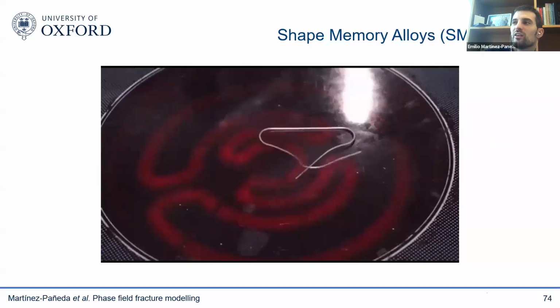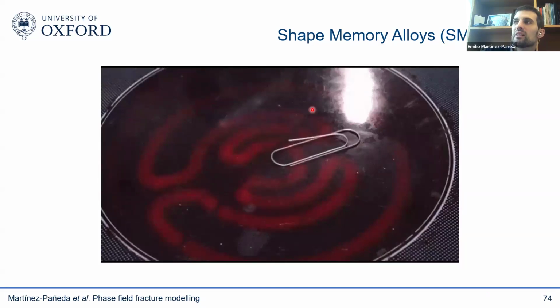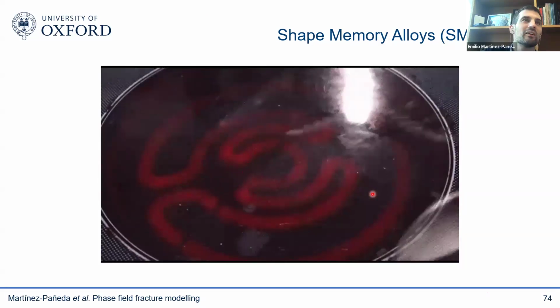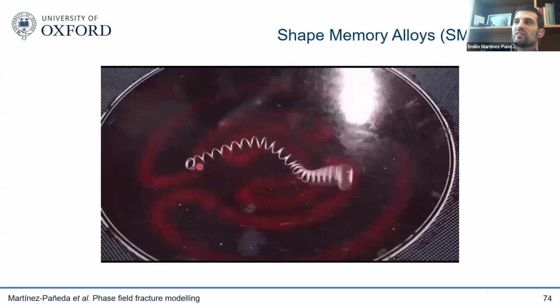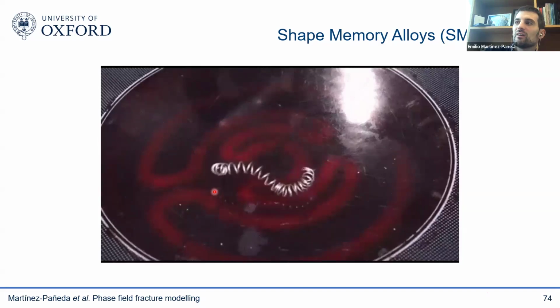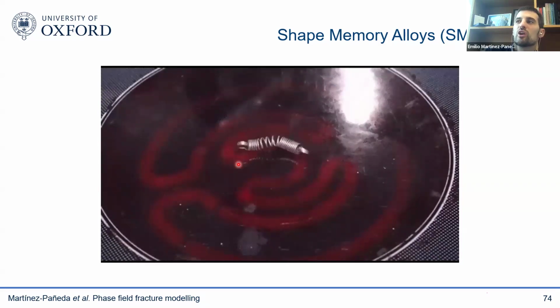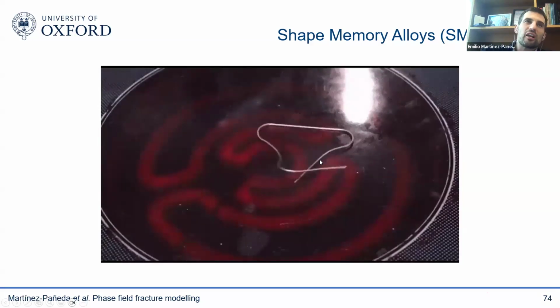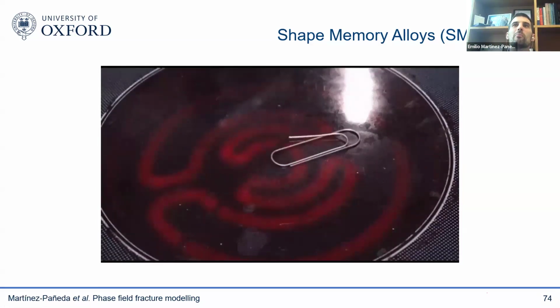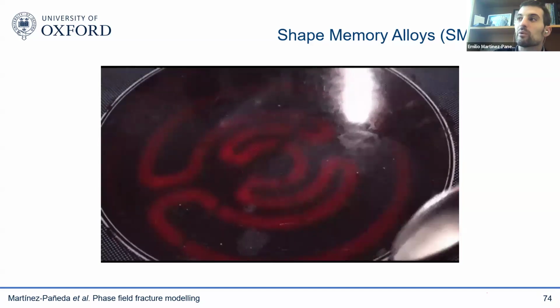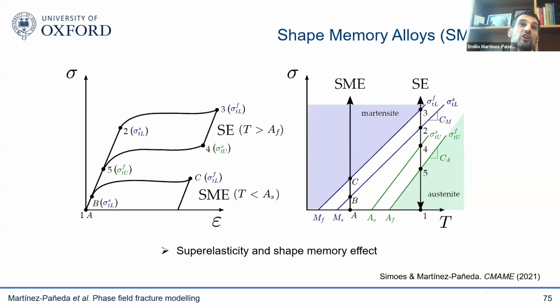So as you can see in these funny videos here, you can take a clip, deform your clip, and then you apply a temperature, and because your material has memory, it recovers its original shape. You see this here, a classic spring. You again apply temperature and recover the original shape. So you can apply a load, deform your clip, but then you can apply a temperature and you go back to the original shape. And the reason why this is happening is because of a phase change from austenite to martensite. So that brings two interesting phenomena. One is called the shape memory effect, which you just observed. The other one is superelasticity. They can go to very high elastic strains and recover their original shape.